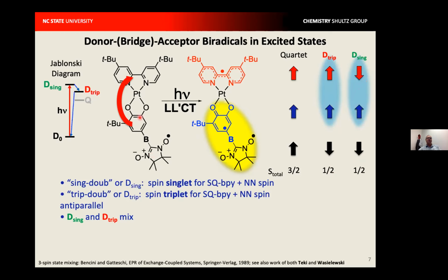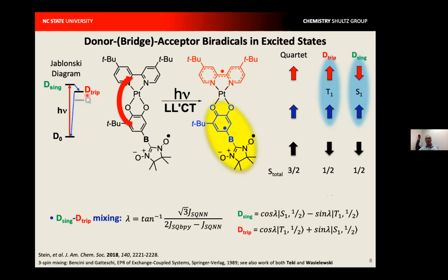Because in the absence of a nitronyl nitroxide, the catecholate complexes make singlet excited states that rapidly decay back down to the ground state. By the same token, you do not intersystem cross to quartet states in these radical-elaborated chromophores. And so photoexcitation by irradiating the ligand-to-ligand charge transfer band produces the D-sing, the singlet chromophoric doublet excited state, that rapidly undergoes internal conversion to D-trip, which now you can observe essentially as the triplet configuration of the chromophore. Then D-trip non-radiatively decays back down to the ground state, but in a very interesting way that I'll hopefully quickly go through here.